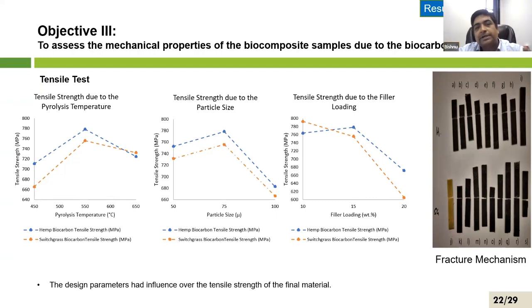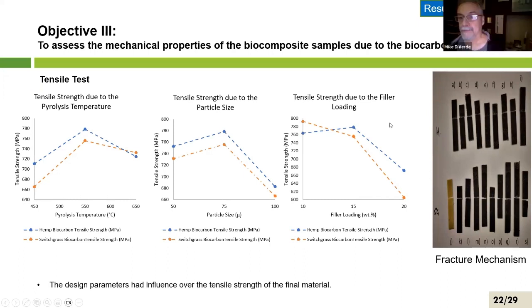When you have a larger particle size inside the resin, that hardens very quickly. It is a big challenge how you mix it so quickly that you get proper dispersion before it gets hardened. So that's one of the challenges that we faced while making this sample. Interesting. Yeah, so these are some of the samples that we tested.